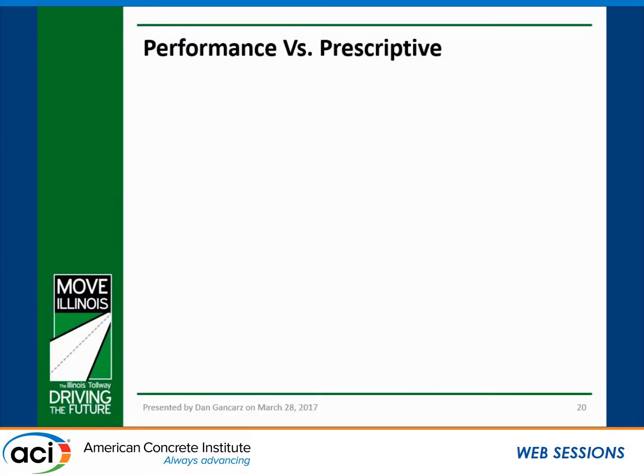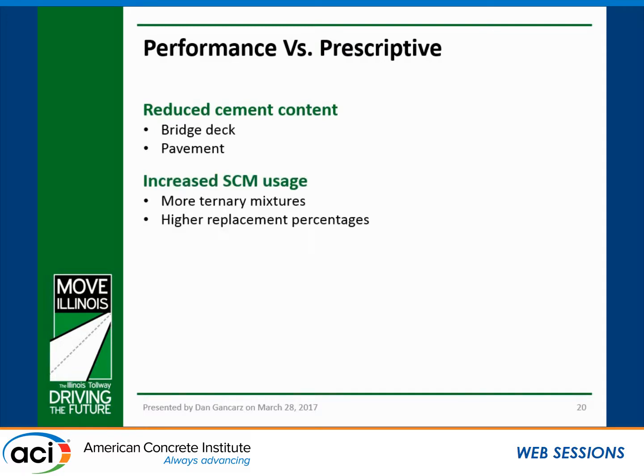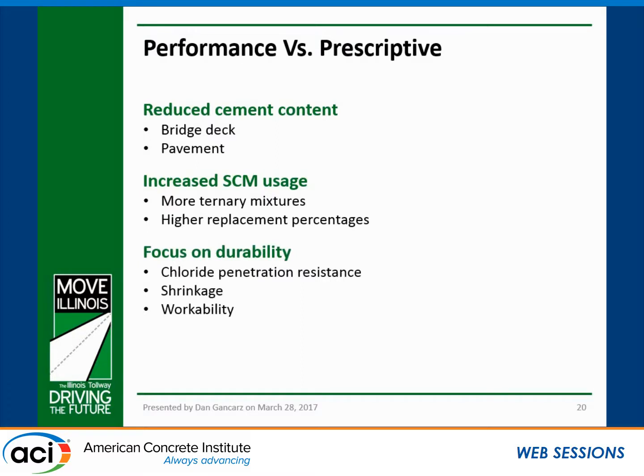So summary and future changes. In general, at the Tollway, we've seen from performance to prescriptive, reduced cement contents in both bridge deck mixes and our pavement mixes. We see increased SCM usage as part of having the requirement for the pavement mixes to be ternary. We've seen that other mixes, although not required to be ternary, producers are selecting to make them ternary because they have the materials available. And now they're becoming more comfortable with higher replacement percentages. And then we also see a focus on durability, not just from the engineering side, but also from producers, contractors. There seems to be more focus on quality control, consistency, and then also the things that affect chloride penetration